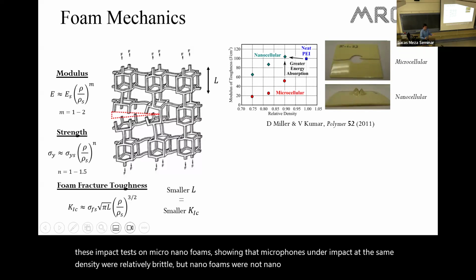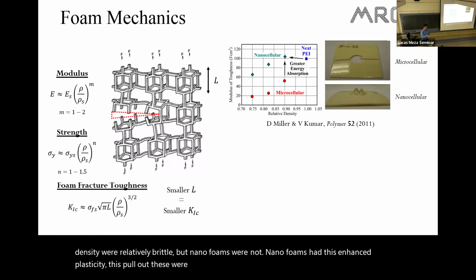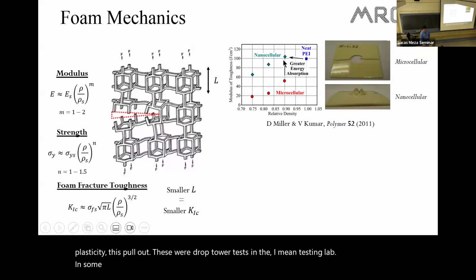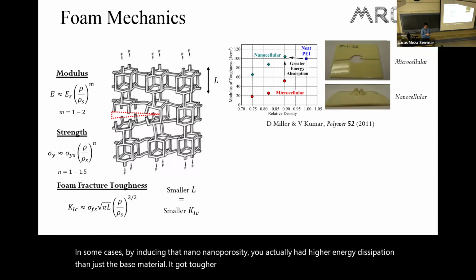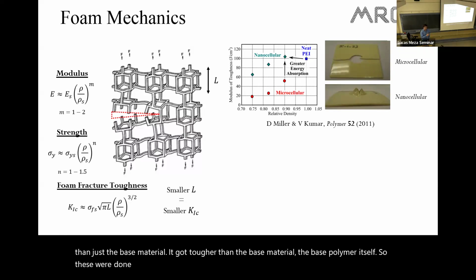Nanofoams had this enhanced plasticity, this pullout. These were drop tower tests in the ME testing lab. And in some cases, by inducing that nanoporosity, you actually had higher energy dissipation than just the base material. It got tougher than the base polymer itself. These were done on PEI, polyether imide, a high temperature, high performance thermoplastic.